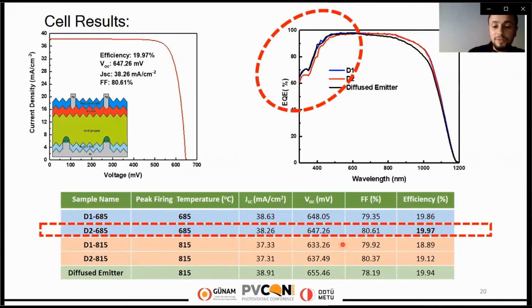If we look at VOC values, this is interesting, of course, because the firing temperature has a very strong effect on VOC values. For higher firing temperatures, the VOC is lower, but for the low firing temperatures, the VOC is higher. But still, for the lower firing peak temperatures, we have high fill factor values.